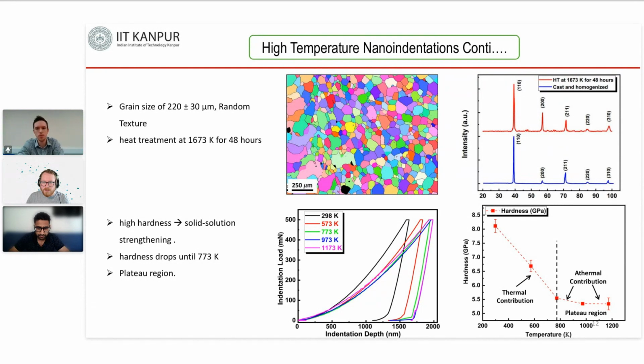We have another question from Aditya, who asks, what is the strain rate of the impact test? I think we have done an indentation test. Maybe I can talk about the impact test in general terms briefly. The strain rate depends on a number of factors, but with the impact test on a nanotest system, we're able to pull the indenter away from the surface and release it, so it accelerates to the sample surface with high energy. Typical impact speeds are around 1 to 2 millimeters per second, but with a sharp pyramidal indenter like a cube corner or a Berkovich, we can generate strain rates of 10 to the 5, 10 to the 6 per second. So again, high energy, high strain rate, particularly useful for studying tool coatings. And again, we can do that at high temperature as well. Okay, thanks, Andy.